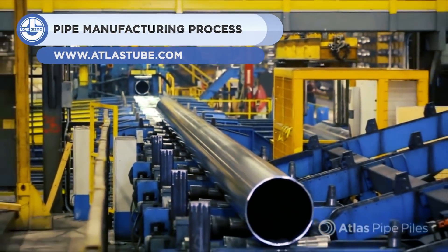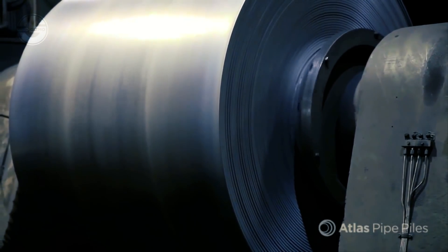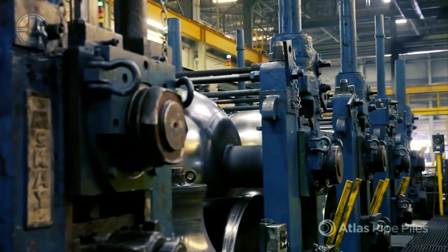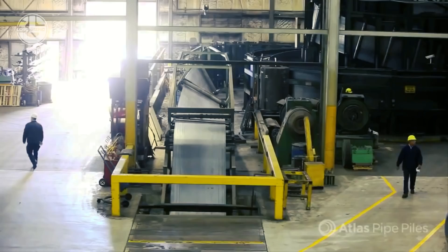For our last stop, we take you to Chicago. This 500,000 square foot facility is where Atlas produces 1,000 tons of pipe piles in a single shift. Every pipe pile is made from hot rolled coil steel. After testing, the coils are slit to size based on the pile diameter and loaded under the tube forming line. Once the steel is uncoiled and flattened, it's joined to the end of another coil. Five forming rollers are used to shape the welded steel into a curve. Each roller bends the pipe a little more deeply until the flat pipe takes on a U-shape. After that, the pipe piles are welded using electric resistance welding. The pile pipe is then gradually cooled by a continual supply of water. An ultrasonic test is performed before cutting it to the required length. Lastly, the weld integrity is determined by pressing and flattening a sample piece.